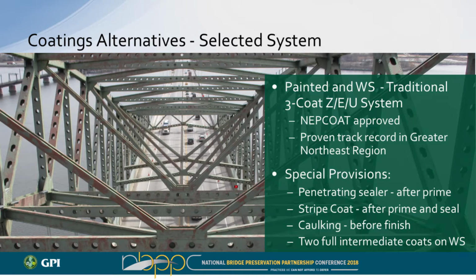Caulking was specified before the finish coat. So you go and you put your primer, your intermediate coat, you come back and you caulk any areas where there is that separation. Again, mostly pack rust, or crevice corrosion where there's an open gap, get the caulk in there, seal out the moisture as best you can, come back and top coat it so that all that caulking disappears. You don't have caulk lines all over the bridge.